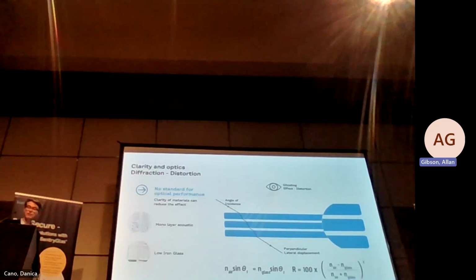Now, a change in the index of refraction due to the change of the wavelength is known as the chromatic dispersion. Now, the more layers in the construction, or the greater the angle of the incidence, it can increase this factor, causing ghost images. And this is why a mono interlayer, a mono acoustic interlayer, can reduce the number of layers and reduce this optical effect. But also the clarity and the coupling effects of an interlayer can add additional benefits to affect the chromatic dispersion.